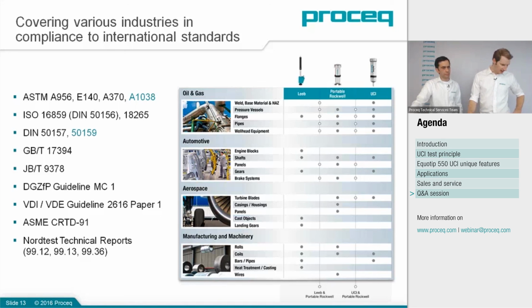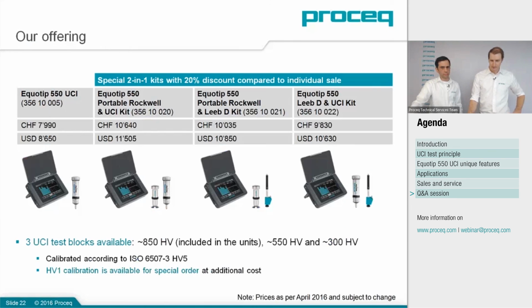And our test blocks, I can show you this here. We are offering three different UCI test blocks. All of them are fulfilling this requirement. So they have 80 millimeter diameter and 16 millimeter thickness. And we are offering three different hardness levels. So the standard test block that is included in the units is approximately 850 Vickers. But then we are also offering one with 550 and 300 Vickers.